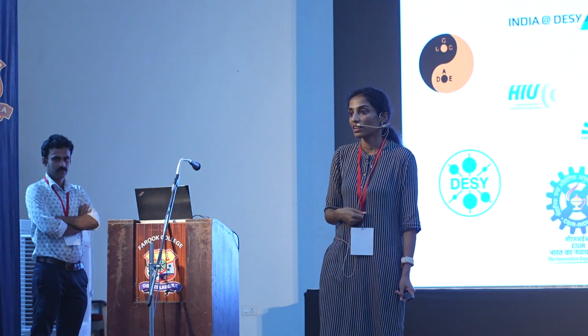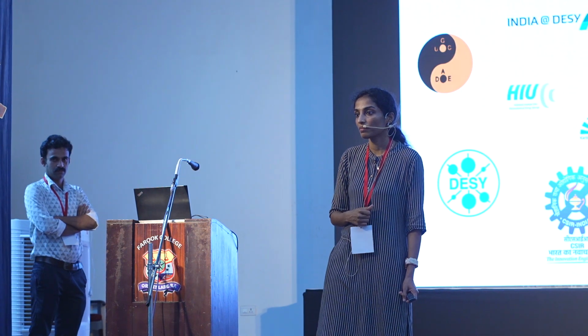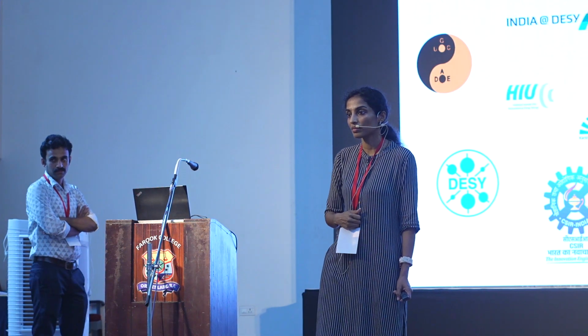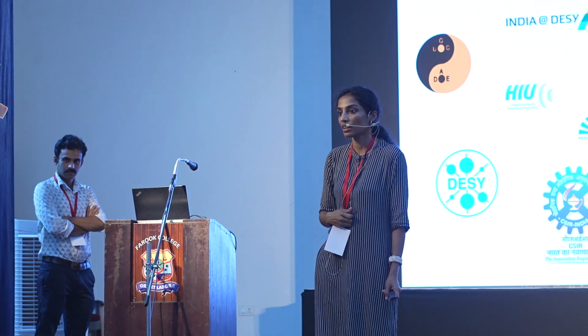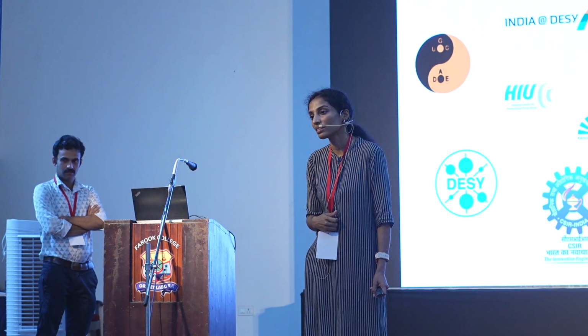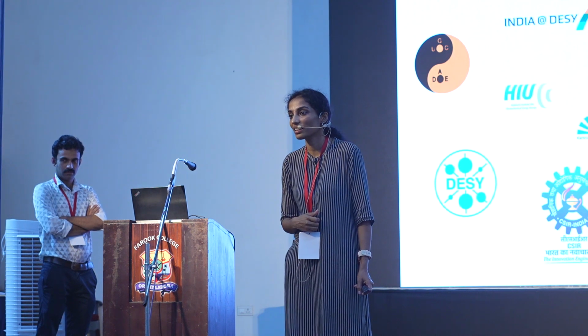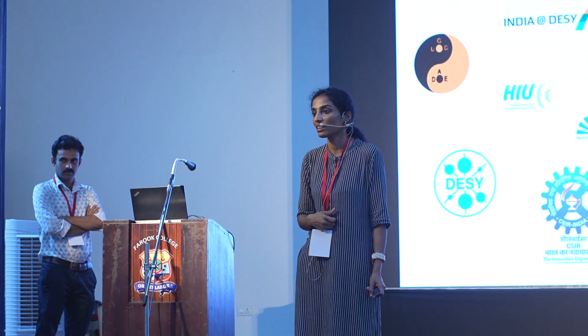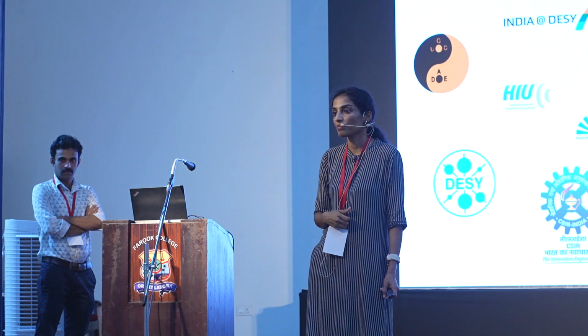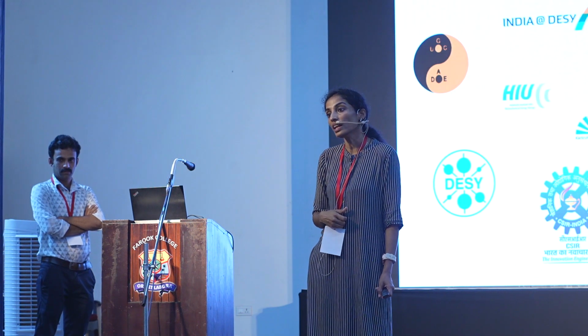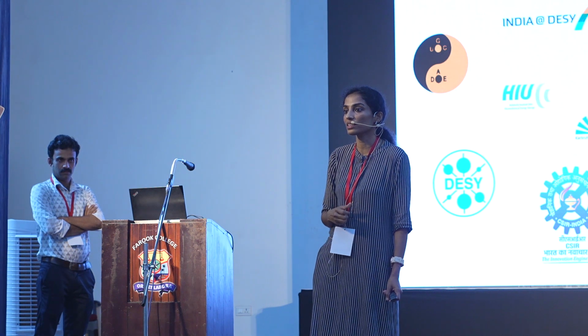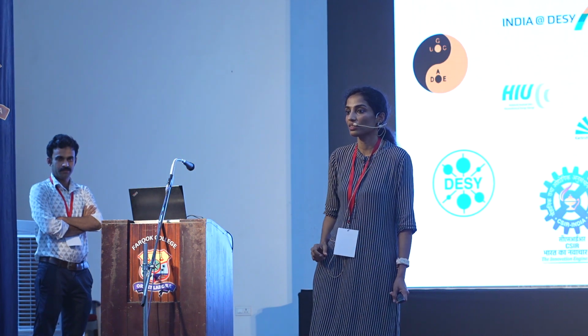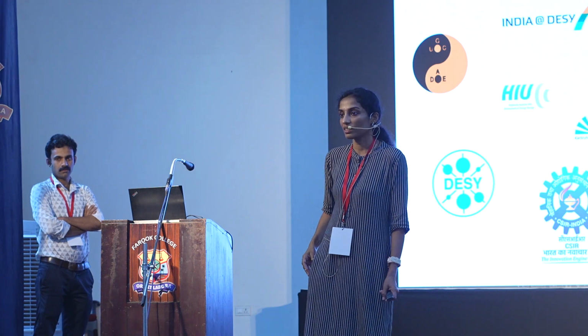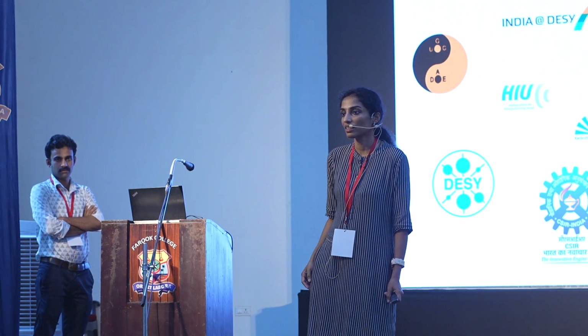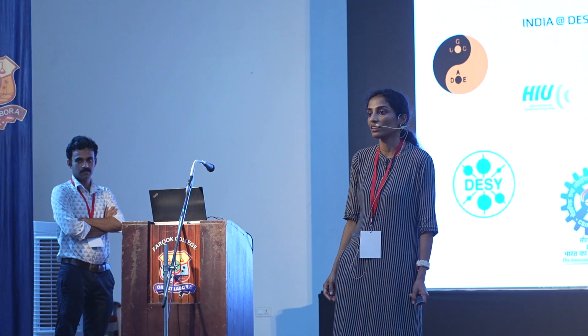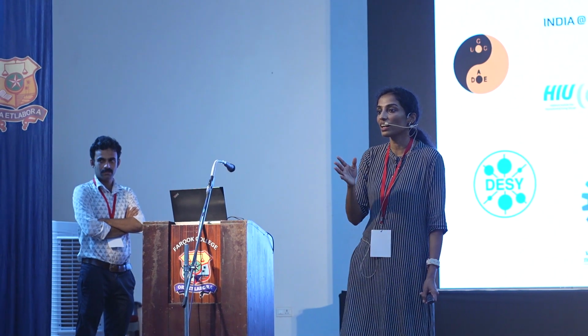For your composite, I understand you are monitoring this process. So you have the electrochemical activity, but you still do not know what the active material is. I mean to say you have a composite still. Sorry, I mean to say you are going 100 cycles. Is there still the integrity of the material? Can you do a bulk powder diffraction to see? Yeah, we do post-mortem analysis. We do Rietveld refinement to make sure the integrity of the phase is maintained, and all these are reversible in nature, essentially. But again, it is only 100 cycles we do.